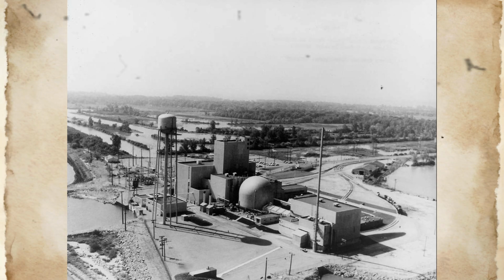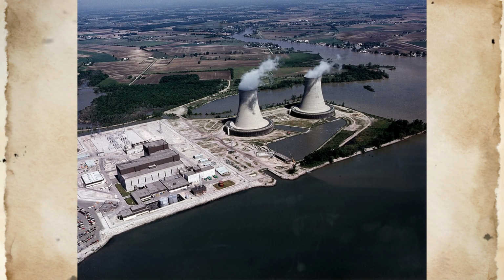The failure analysis demonstrated that the weld fatigue was a predictable consequence of the thermal and mechanical loading conditions that the mounting system had experienced during reactor operation, rather than a random material defect or unusual service condition. The mounting welds had been subjected to thermal expansion and contraction stresses during each reactor thermal cycle, and these stresses were concentrated at the weld interface where material properties and geometric configuration created stress concentration factors that accelerated fatigue crack initiation and growth.